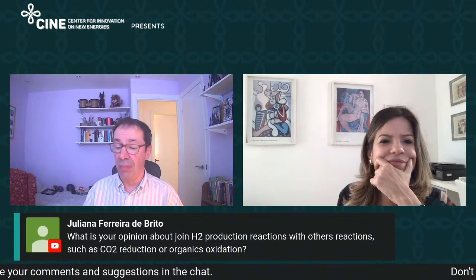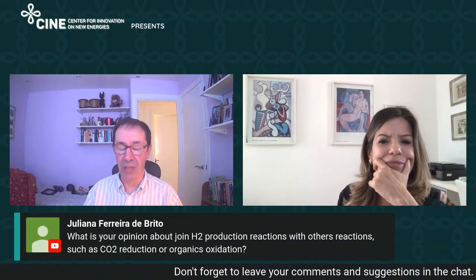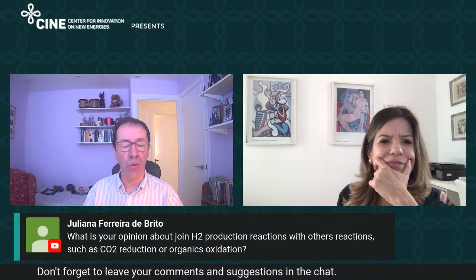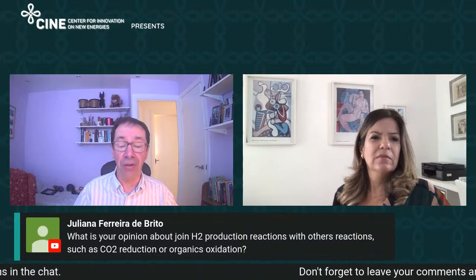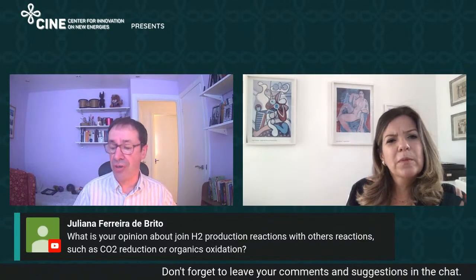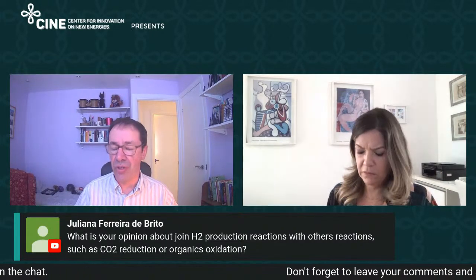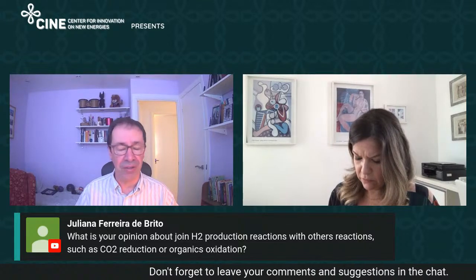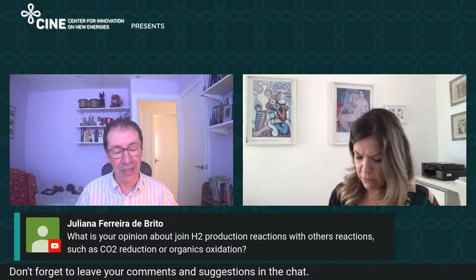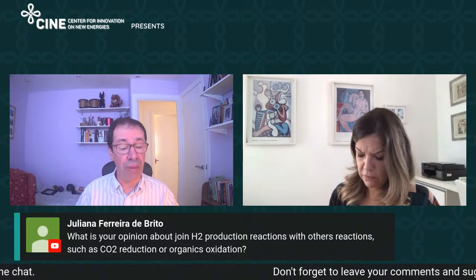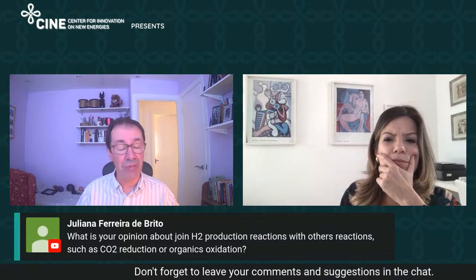Absolutely interesting. So this is a question about should we be going beyond water splitting, either to reducing CO2 or to oxidizing something else. So reducing CO2, of course, is interesting. It's also hard. The catalysis of CO2 reduction is challenging. I gave you one brief example of that, the reduction of CO2 on titanium with silver particles. I didn't mention the quantum yield, which was tiny. But clearly the idea of driving either CO2 reduction or maybe even more challenging nitrogen reduction would be interesting.